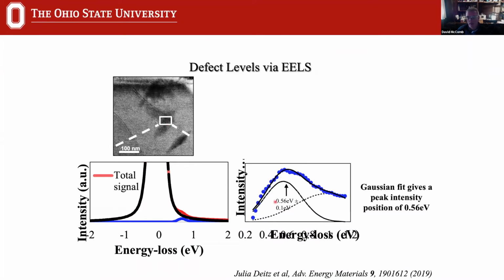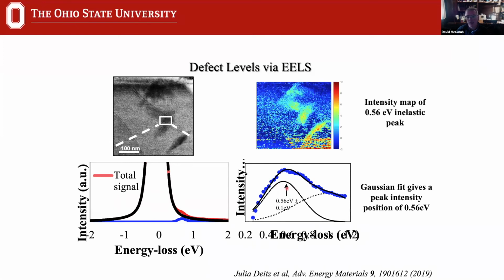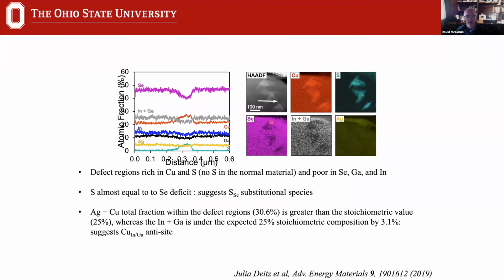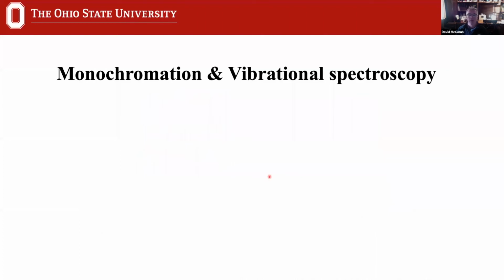Again, we can fit to our Gaussian here, and then we can show that that peak is indeed associated with a transition at 0.56 eV, which corresponds to that trap intensity that we saw in the scanning DLTS. And then we can map the intensity of that peak and show that it really is correlated with the defect. So this is really the first time that we've been able to identify a defect within a full-scale device, localize it, and even go on to identify the chemistry, which again I'll skip over. We were able to report in this paper in 2019 the exact chemistry of this device and the chemistry of this defect, and correlate that with the known electronic properties.